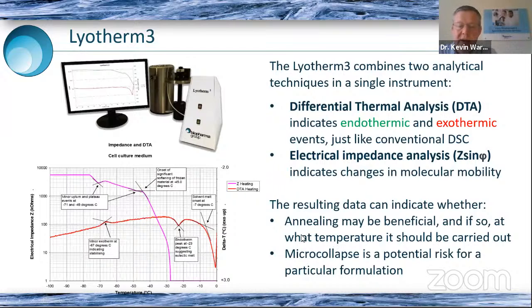What we might also be interested in is, is it worth using annealing? You might have heard the term annealing, and this tends to happen during the freezing phase of freeze drying. So annealing involves taking the frozen material and warming it to encourage things to become more thermally stable, or perhaps to encourage the ice crystals to grow. And so the impedance can give us an indication of what temperature, if we go above that temperature, we're going to see increased mobility and hopefully more accelerated changes and more effective annealing.